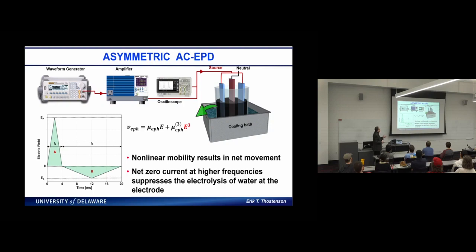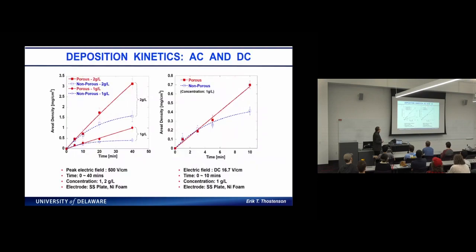We can also control the process quite a bit by using what we call asymmetric AC EPD, where we can limit the amount of electrolysis by having a zero net integral of our wave. But because it's nonlinear, it moves a little more in one direction. So it moves a lot under the high voltage because of the electrophoretic mobility, and then under the lower voltage, it doesn't move back as much. So we get this net movement in the mobility, and we spend a lot of time on this. I mentioned we've studied the deposition kinetics. It depends on a lot of different things: what our electrode is, what our concentration is in the dispersion, and what our electric field is. But it's something where we can often just deposit in a few minutes and get a very uniform coating onto the fibers.